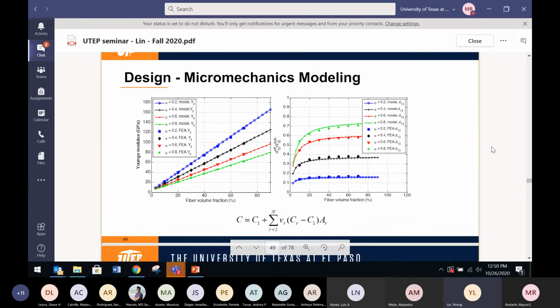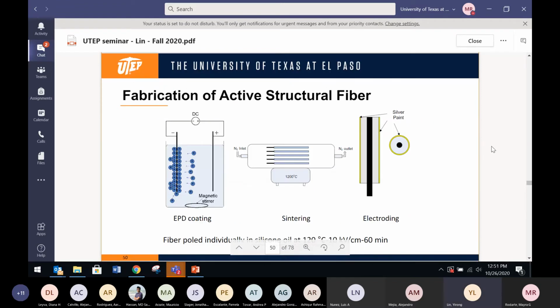Some modeling, right? Some equations. I know nobody likes equations. I'll be brief. Basically it tells you that by controlling the coating thickness, you can control the Young's modulus, and you can control the piezoelectric response. Next slide. Okay, so this is how we make them. This is an interesting process. You have these nanoceramic particles and you disperse them in organic solutions. Once you apply DC current, all these particles will deposit onto the cathode. Then once you do the sintering, you have a ceramic coating on the outside of the fibers you use. And then you can do post-processing to make them piezoelectric. Next slide.